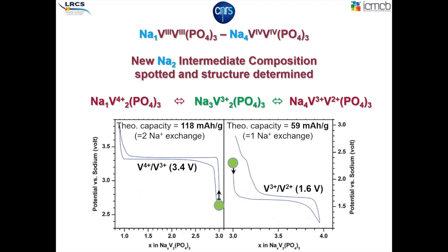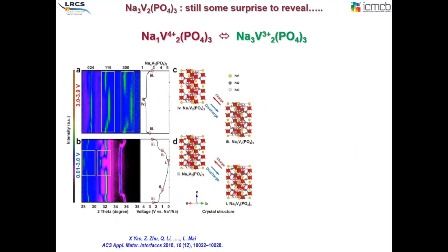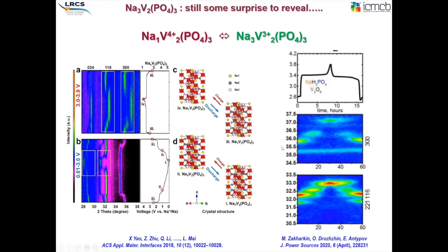So this system, apparently very simple, gave us some very nice surprise recently. Gave us, but also some others. We have to acknowledge that some people already identified that in this apparently boring redox plateau, some intermediate phases would appear somewhere in the middle of the extraction of sodium from Na3. This was even more clearly identified and described by our colleagues from Russia in the Antipov group, who from Na3 to Na1 identified the appearance of a new phase at mid-charge.